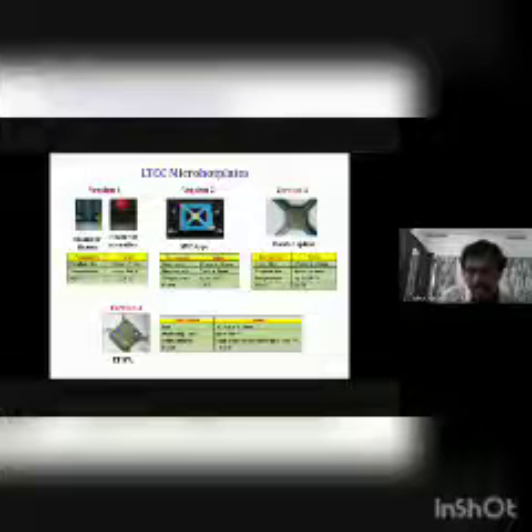But in the case of micro hot plates, where we are using this printed electronic mechanism or screen printing, here you can see the various versions of hot plates available with us. And here we can see that by using less than 1 watt, meaning 0.9 watt, we can attain a temperature of 300 degrees Celsius in a 3 by 3 mm range by using printed electronic mechanisms.